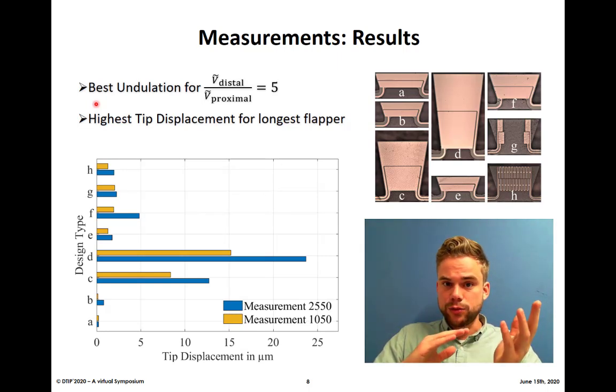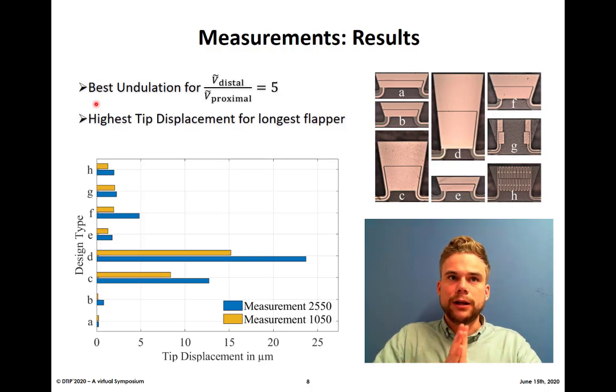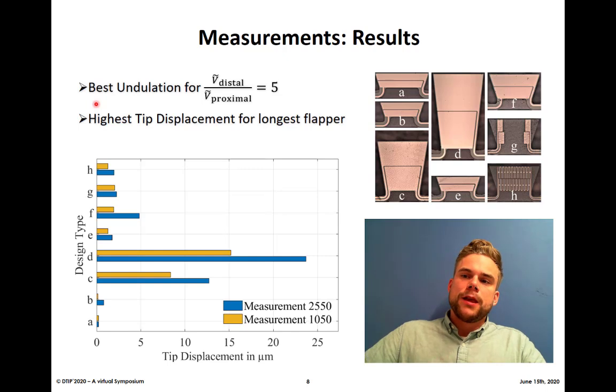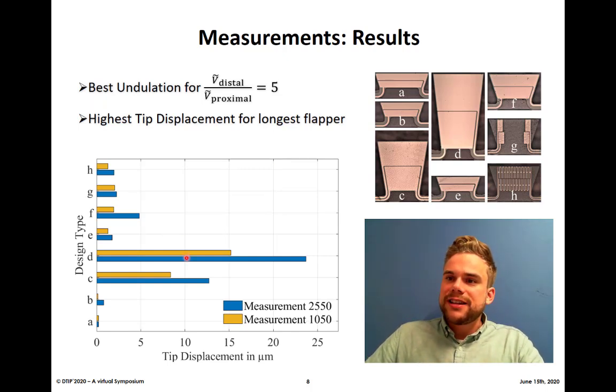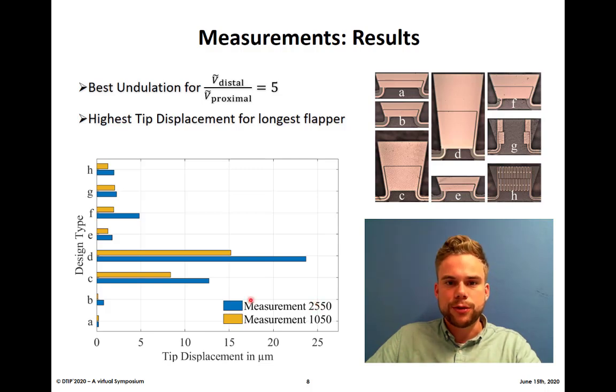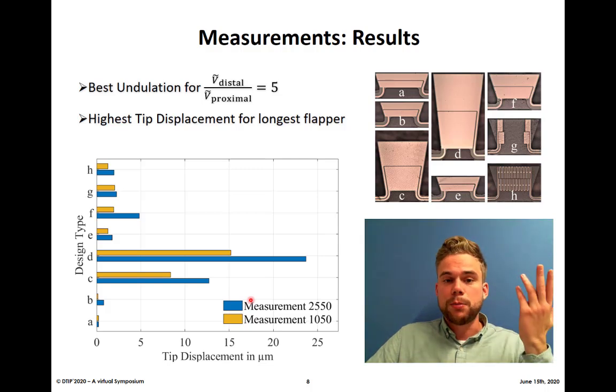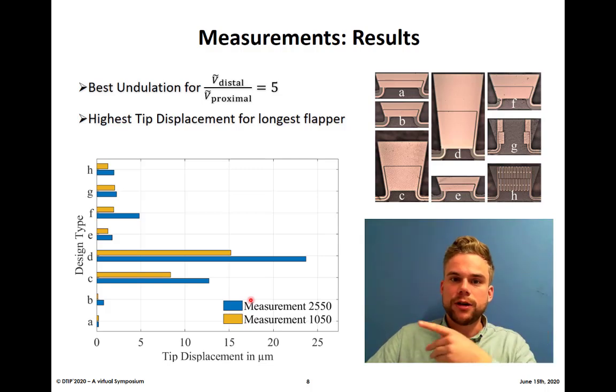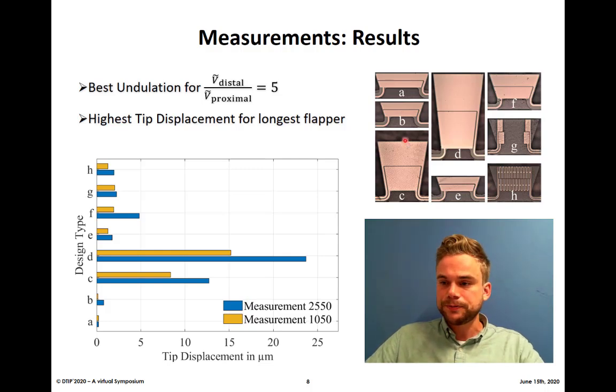On the other hand, as a comparison, we had 25 volt as well. So first of all, the ratio of 5, and secondly, a ratio of 2. So we see in the results here that the tip displacement is indeed higher for the ratio of 2, but the undulation is not. In that case, of course, if we apply a higher voltage on the proximal electrode, it will bend more, and thus induce a higher tip displacement at the end of the electrode. But we figured that the undulation is worse in this scenario.